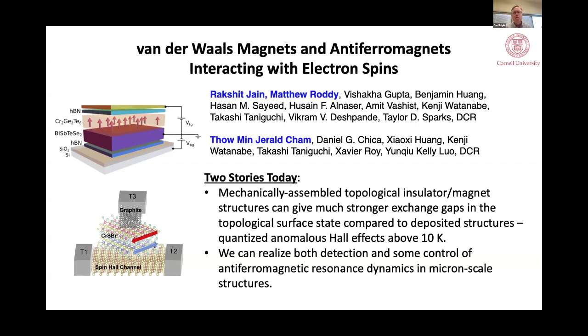So I'll actually talk about 2 stories that I hope will be of interest. One has to do with creating topological states by a proximity interaction between a topological insulator and an adjacent magnet. And what we've done there that's different from previous work is we use mechanical stacking, the techniques people use for 2D materials, to create those interfaces rather than deposition techniques. And it turns out that creates a dramatic difference in the strength of exchange interaction between the magnet and the topological surface state. We can see quantized anomalous Hall effects above 10 Kelvin in these materials, which is about a factor of 100 higher temperature than what's been seen previously with the deposited structures.